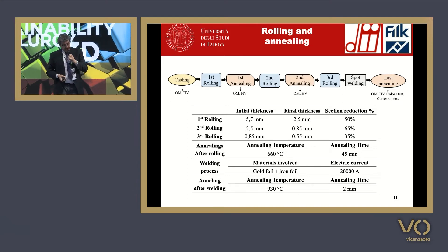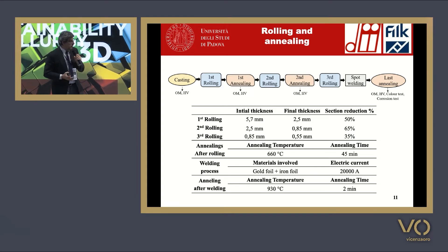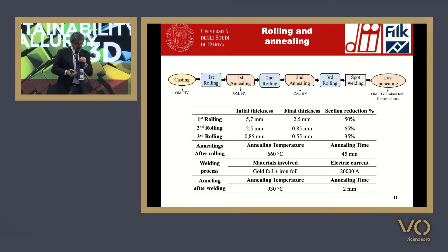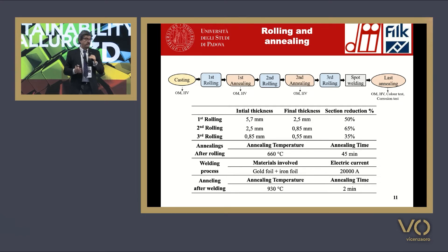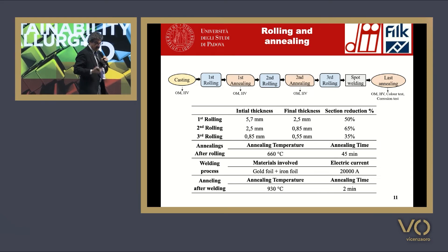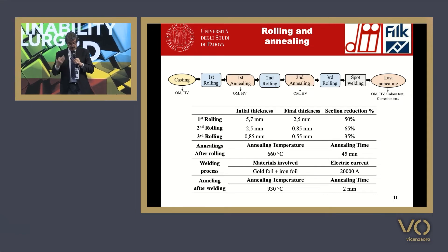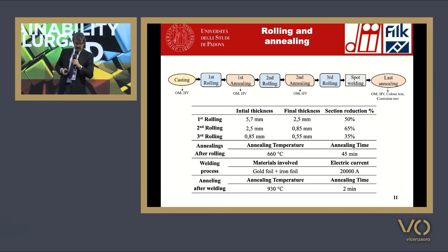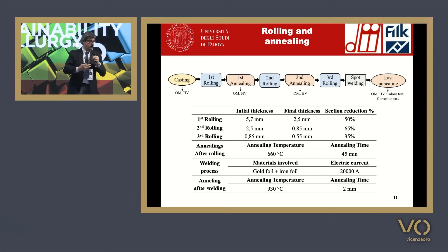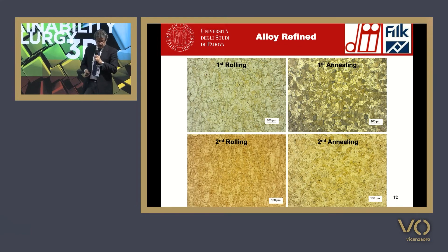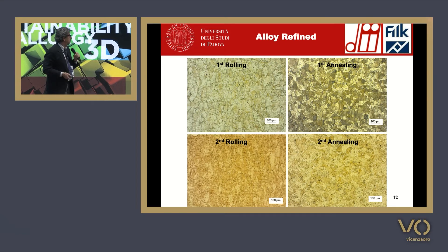The other term is recrystallization. When we deform a material — gold alloys, platinum alloys — during plastic deformation, the alloys reduce grain size, but with an increase in the internal energy of the alloys. Because during deformation, part of the energy is absorbed by the alloys to reduce grain size. But when the temperature of the alloys is raised, there is a behavior called recrystallization, which produces the nucleation and growth of strain-free grains. These strain-free grains reduce tensile strength and hardness, but essentially increase the ductility of the alloys. This is the process that occurs during annealing.